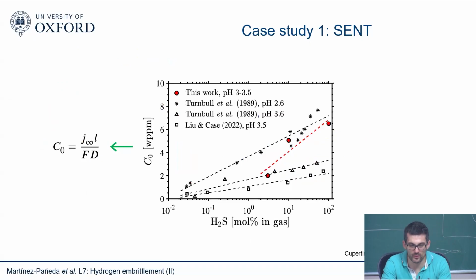And this seems to agree with what we see in the experiments. There are some classic experiments by Turnbull and by other people, and they measure some changes. There's a different pH, so it's not 100% comparable, but you see a difference in the hydrogen concentration with the H2S.